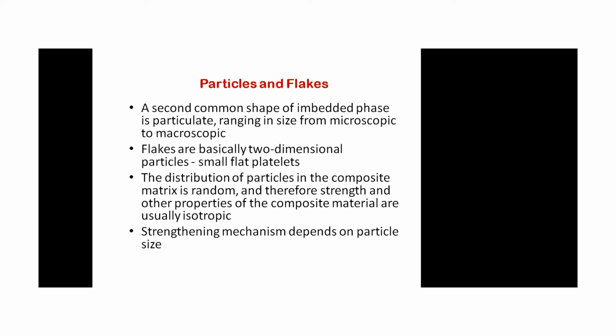The strengthening mechanism depends on the particle size. The finer the particle, the more the strength of the material, because Zener pinning and other dispersion hardening mechanisms work there. So as you decrease the particle size from mm to micron or micron to nano, the strengthening is different.